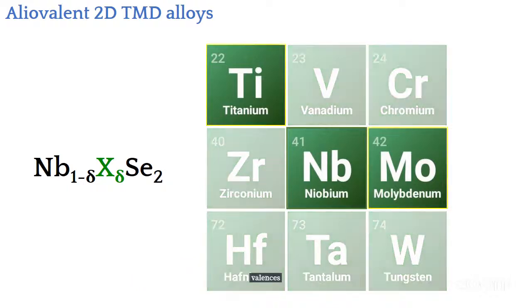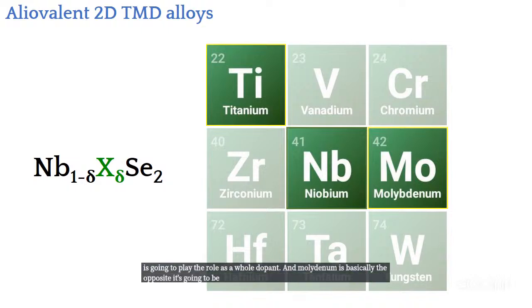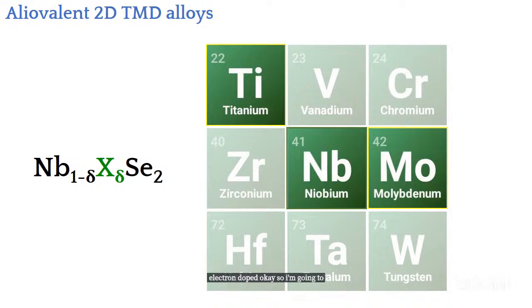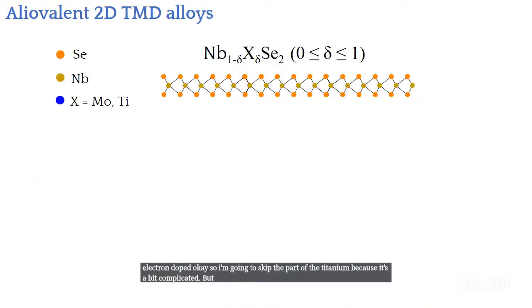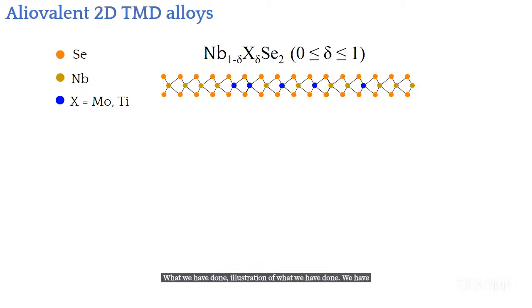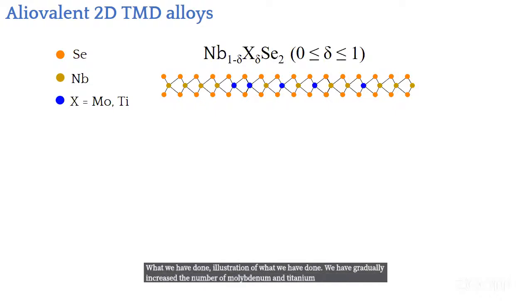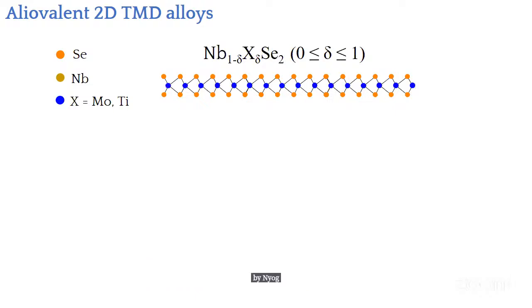Okay, so what we have done is basically to merge in the same material niobium with titanium, which has one less electron in the valence band, and molybdenum, which with respect to niobium has one more electron. So in other words, titanium is going to play the role of a hole dopant, and molybdenum is basically the opposite. It's going to be electron doped. I'm going to skip the part of the titanium because it's a bit complicated. This is more or less an illustration of what we have done. We have gradually increased the number of molybdenum and titanium atoms replacing niobium in this plane, okay?